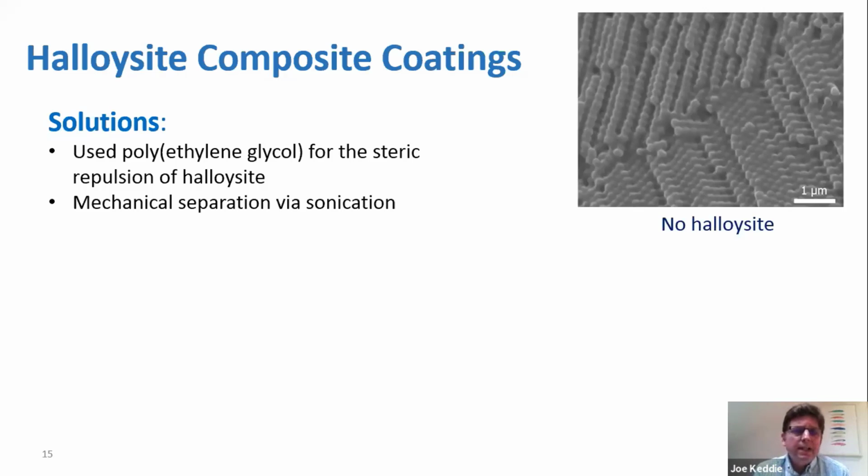So we added polyethylene glycol that introduced some steric stabilization for the halloysite. Also started using some sonication to make sure we were dispersing the halloysite quite well.